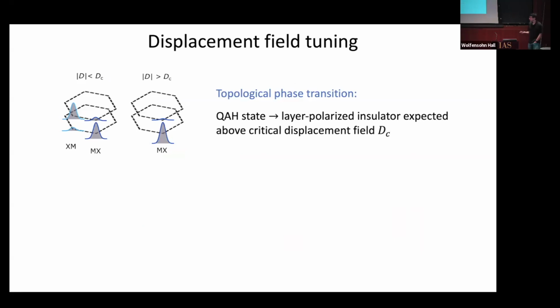You also heard earlier in the talk and earlier in the conference that displacement field is a tuning knob for the topology of the ground states that you get. So in the low displacement field limit, you expect the weight to be equally occupied on these two sublattices, which are partially polarized for a given site in different layers. But as you apply a displacement field, you favor all of the holes occupying just one of the layers. And so you form effectively a triangular lattice. This is a trivial insulating state. And so you expect the topological phase transition as a function of electric field as well.